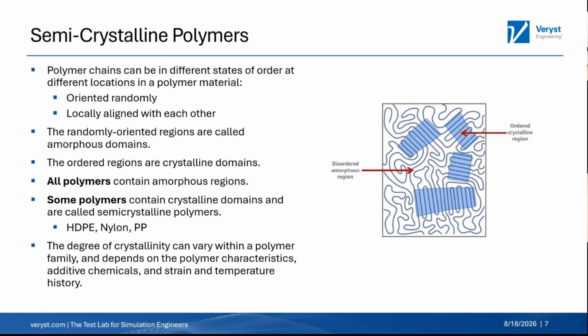And just as a note, the actual degree of crystallinity can vary strongly, even within different grades of, let's say, polyethylene. It depends a lot on the polymer characteristics, like the molecular weight of the polymer chains, if there are certain additive chemicals added that can either promote or hinder crystalline formation, as well as things like strain and temperature history. So by stretching polymers, you can actually have strain-induced crystallization, just for example. So this is not a case where you can say to me, okay, I have this polypropylene, how semi-crystalline is it? I can't answer that question for you necessarily, to a reasonable degree of certainty. We have to measure each individual polymer and sometimes each individual product.